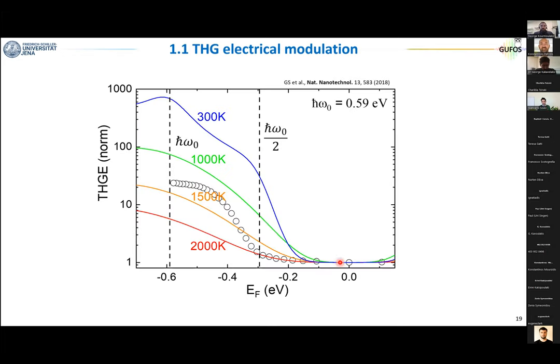And now, if we take again our experimental data, so the white points, and overlap them with the theoretical curves, but this time we use higher electronic temperatures, I don't plot the 0 Kelvin, I start from room temperature, 300 Kelvin, you see that our experimental data are also very far from 300 Kelvin, this is a logarithmic scale, and instead they fit quite well with temperatures in the range of 1000 to 2000 Kelvin. And now I go back to the previous question. Where does the linear response, the Chi1, play a role? The Chi1 plays a role because the fundamental beam is absorbed, and by absorption, it will increase the temperature.